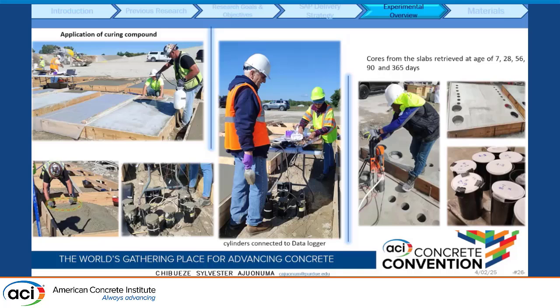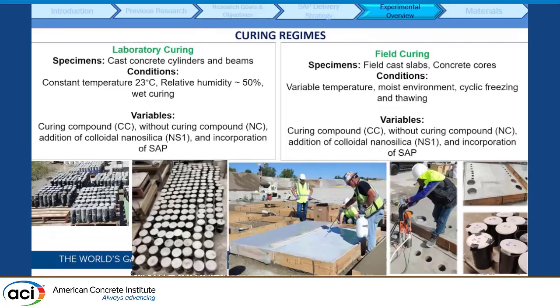Also, I need to emphasize that all the slabs were instrumented using thermocouples to evaluate the temperature gradients. This is a picture of the thermocouple. At testing ages of 7, 28, 56, 90, and 365 days, cores were extracted from the slabs in the field and taken to the lab for testing.